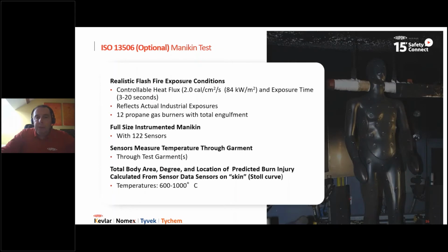Now, as I said, all these tests are done on fabric samples only. So you're not getting a real assessment of a full garment. In order to assess a full garment, the mannequin test, according to ISO 13506, is a very good method indeed, because here you can dress a mannequin with the garments you want to wear, and you are exposing that to a full flame engulfment between 3 and 20 seconds. The industrial standard in Europe is 4 seconds.